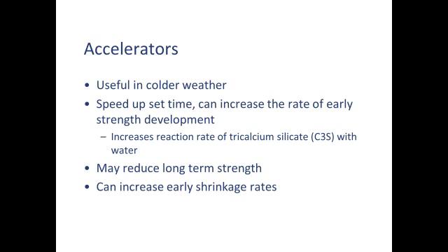Now, accelerators tend to, like I said, affect the C3S. That's the shorthand we use to denote the early strength portion. When you change the early strength, you can start stripping your concrete faster. You can start working on it faster. That may or may not affect your long-term strength because they're somewhat unrelated. If your early strength is generated in the first day or 3 days, your long-term strength may not even begin. You may not even begin to generate significant amounts of the dicalcium silicates for a week, maybe 10 days. So there's a period of time where one tapers off and one begins.